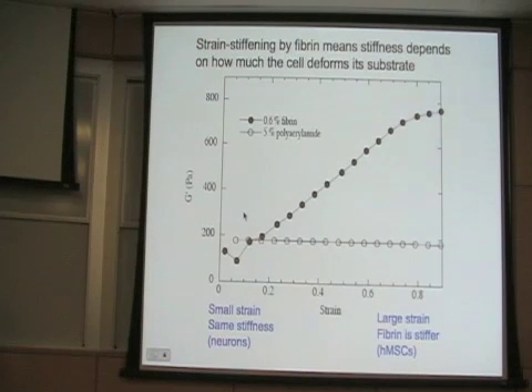So now back to the cell business. The reason this is, I think, interesting for mechanical sensing is because different cells pull with different amounts of enthusiasm. So the endothelial cells we looked at appear to pull with very large forces, hundreds of kilopascal. But there are other cells, like neurons, that pull very little, a few tens of pascal maybe. So some things pull a little bit, and therefore we put small strains on a material. Some things pull a lot, therefore put big strains on the material.